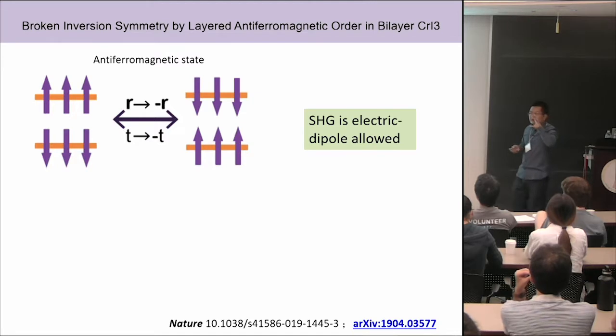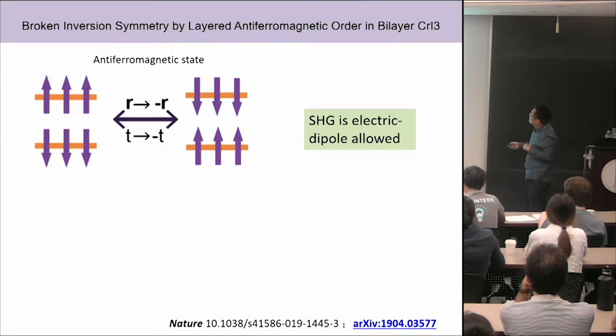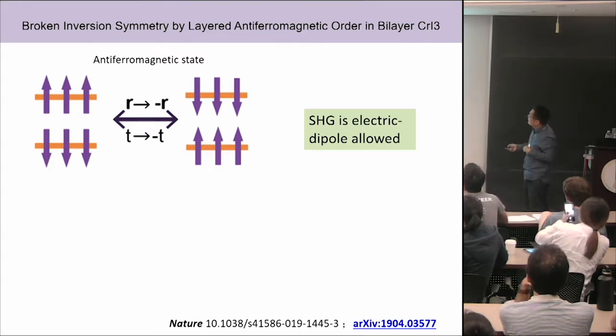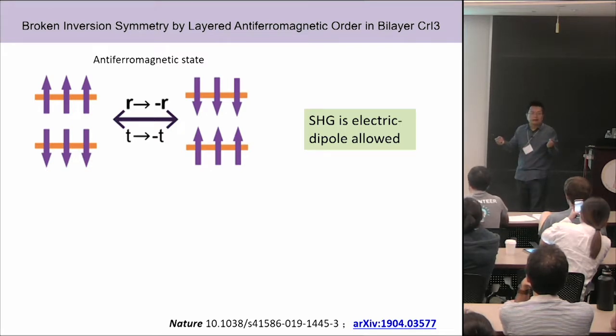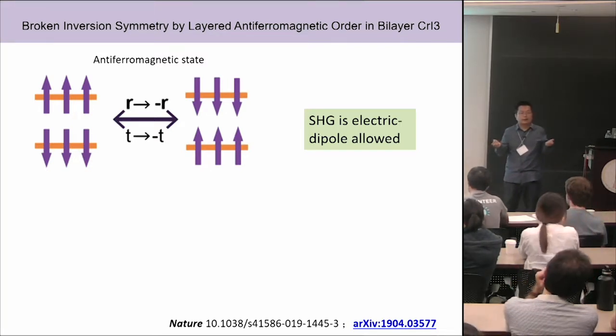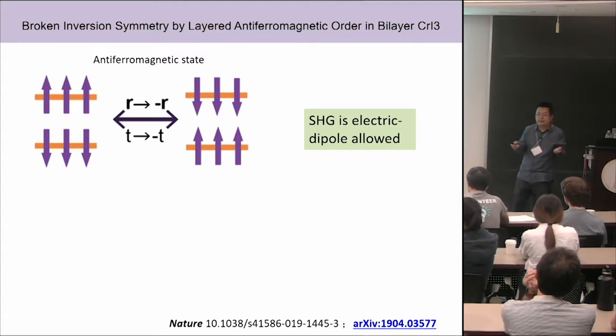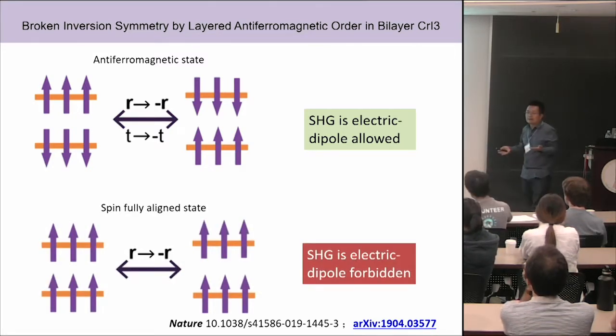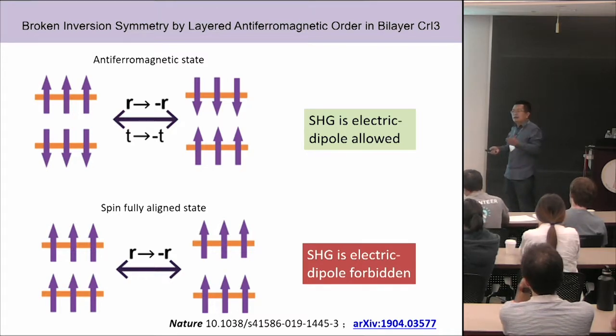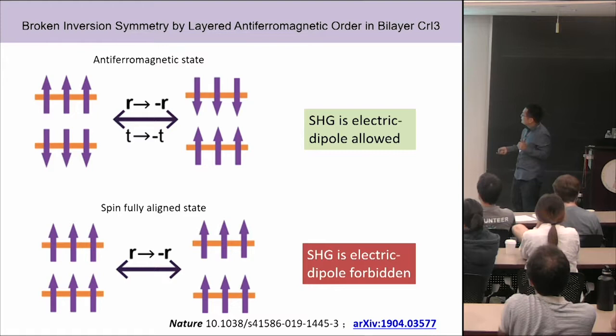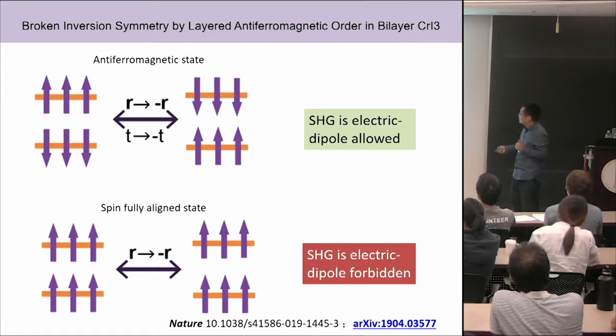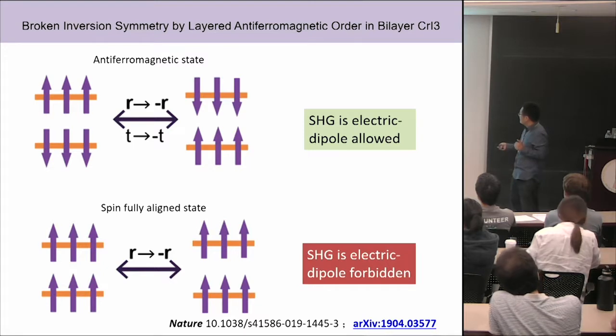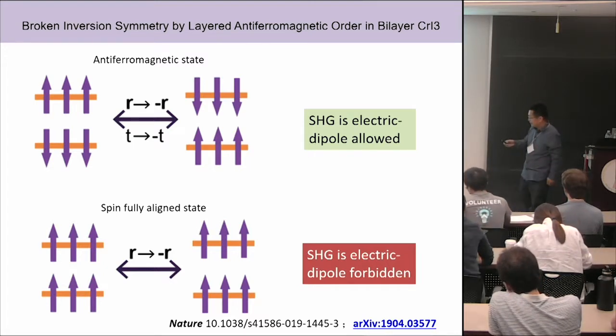But now if we add this spin structure into the system, you see in this anti-ferromagnetic ground state, right? If you do the inversion symmetry operation, now the left-hand state is going to go to the right-hand side. These two are different states. So what it means is inversion symmetry actually breaks due to this layered anti-ferromagnetic order. Therefore, the second harmonic generation should be allowed. Now, if I apply a large enough magnetic field to turn the system into this ferromagnetic state, then the inversion symmetry actually restores. Then the second harmonic generation should be electric-dipole forbidden again, right?